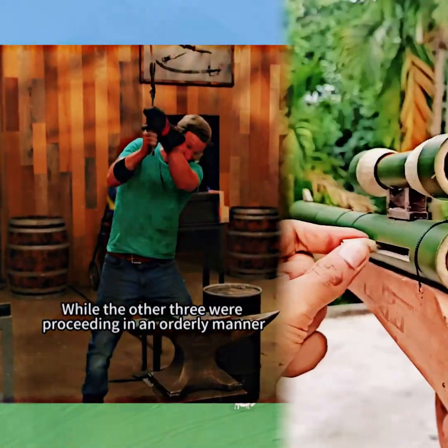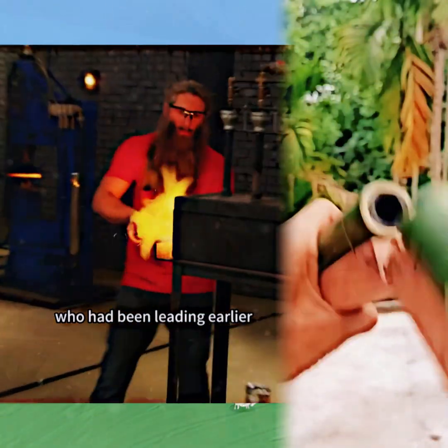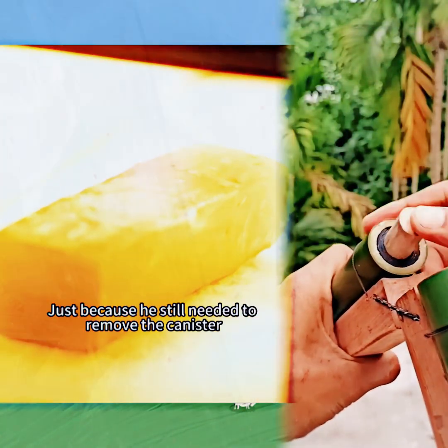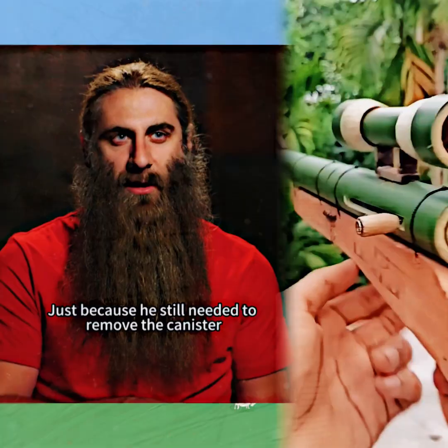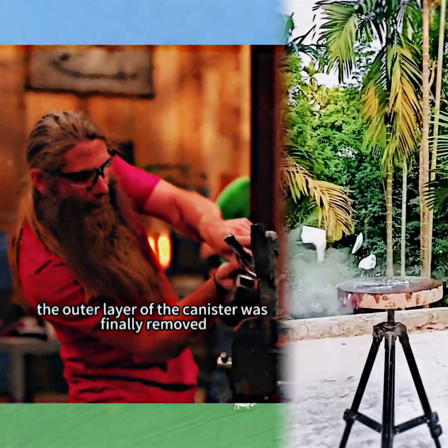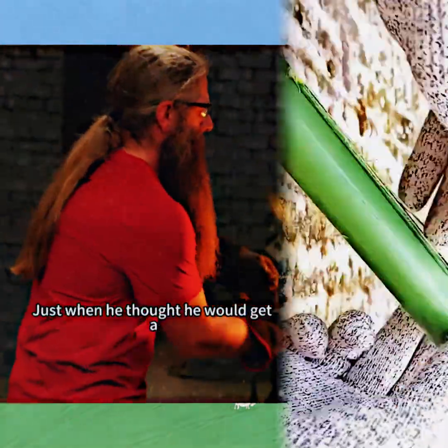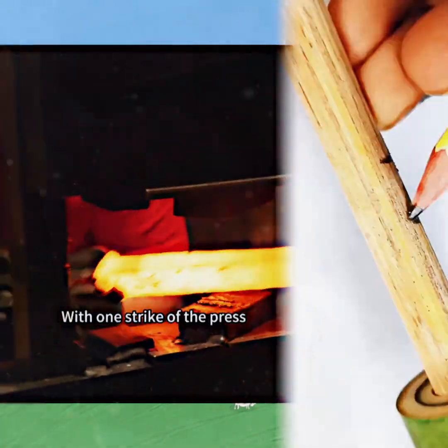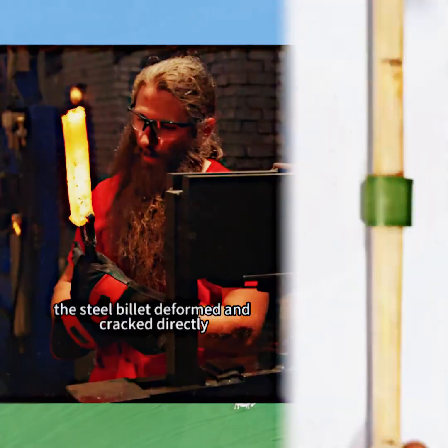While the other three were proceeding in an orderly manner, Alan, who had been leading earlier, started to fall behind, just because he still needed to remove the canister. After a lot of hammering, the outer layer of the canister was finally removed. Just when he thought he would get a piece of fine high-carbon steel, an unexpected situation happened. With one strike of the press, the steel billet deformed and cracked directly.